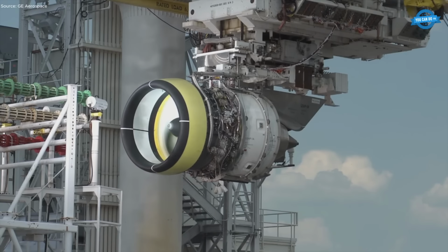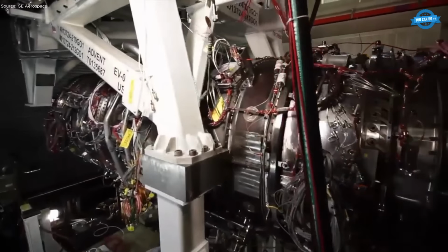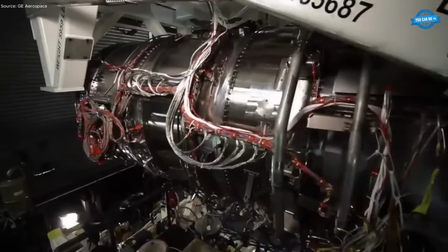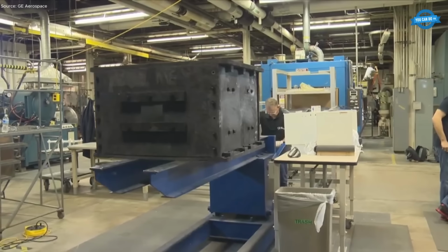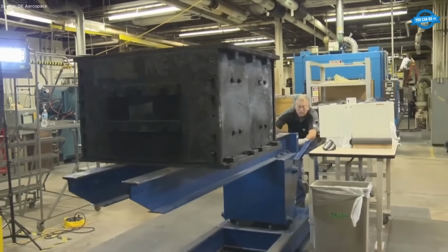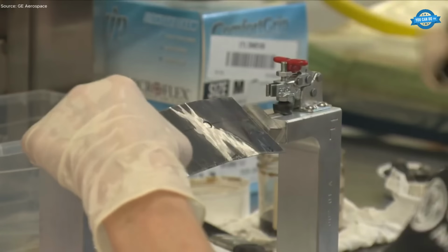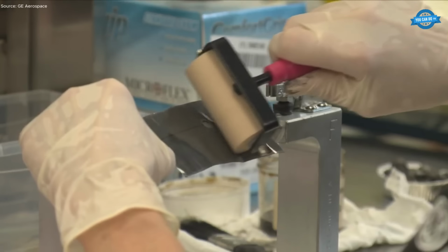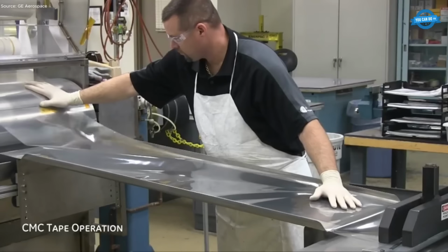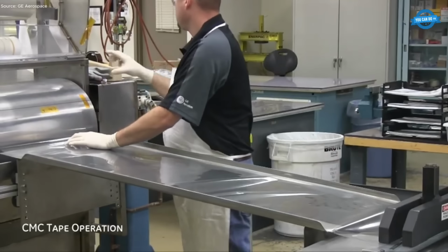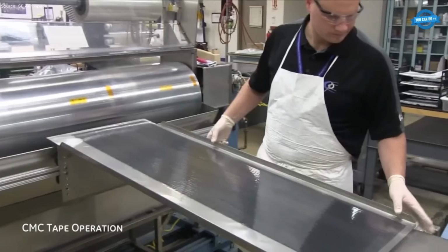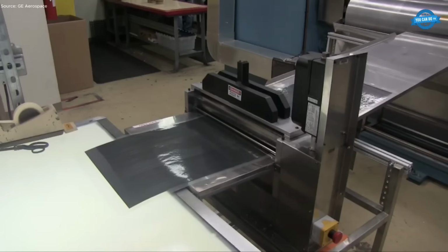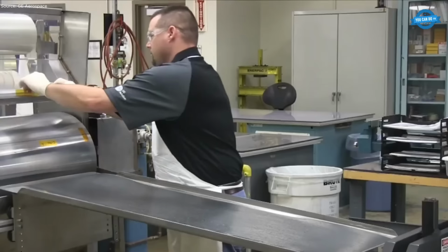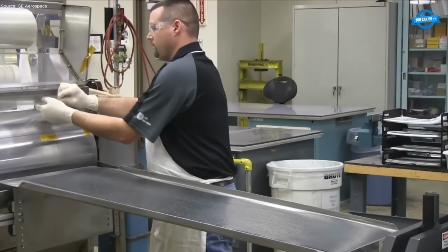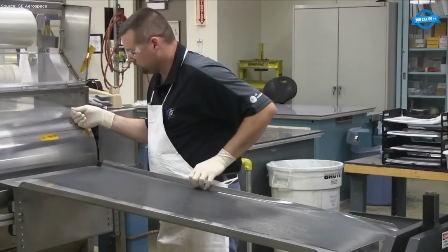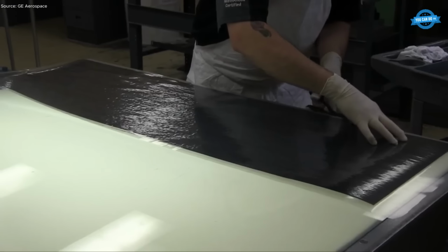Performance advantages are direct and quantifiable. CMCs have roughly one-third the density of superalloys and tolerate several hundred degrees Celsius higher service temperatures. This reduces cooling air requirements and enables higher cycle temperatures, translating into improved thermal efficiency, higher thrust, and measurable fuel burn reductions. Manufacturing challenges remain: consistent interface quality, controlling residual porosity, machining yield, and qualification across many flight hours, but ongoing process automation, fiber supply scaling, and rigorous test programs are addressing these barriers.